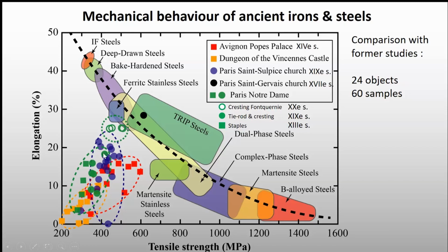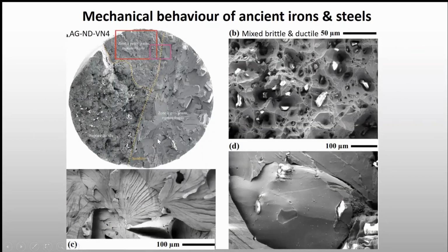So here are the results which we have, and what we can see when we look into the microstructure and the fracture zone. And this is really interesting, the role of the welding lines, which we can see here in yellow. We can see that in different parts of the welding lines, we have different microstructure, and we have different behavior because we have different microstructure. Some of it ductile and some of it fragile.